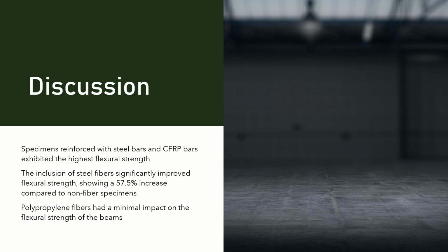In our discussion, we observed that specimens reinforced with steel bars and CFRP bars exhibited the highest flexural strengths. Including steel fibers in the concrete significantly improved its flexural strength, showing a 57.5% increase compared to non-fiber specimens. In contrast, polypropylene fibers had a minimal impact on the flexural strength of the beams.